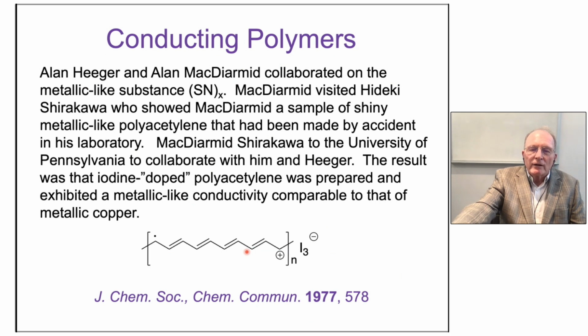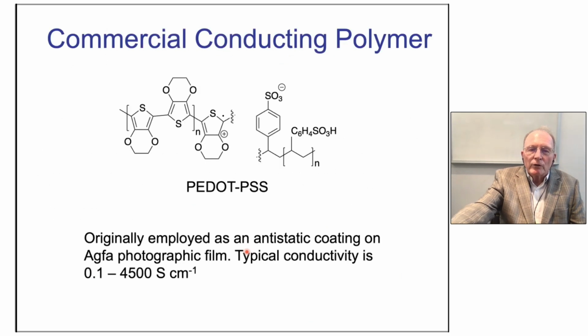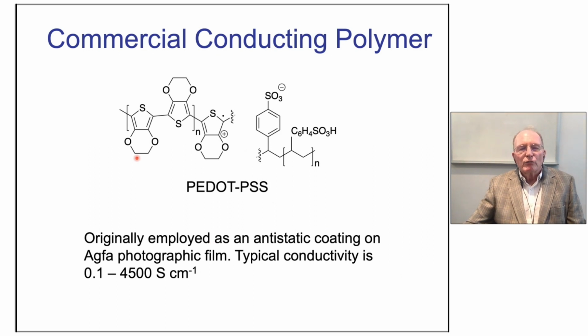And metallic and organic semiconductors, well, I'll go on and say PEDOT:PSS is really, I think, still the best commercial conducting polymer. And this is both protonically doped and also, again, oxidatively doped by forming radical cations. And it was used by AGFA for an antistatic coating, huge quantities. Its typical conductivity is up to 4,500 Siemens per centimeter. And it's a really useful alternative to metallic electrodes.